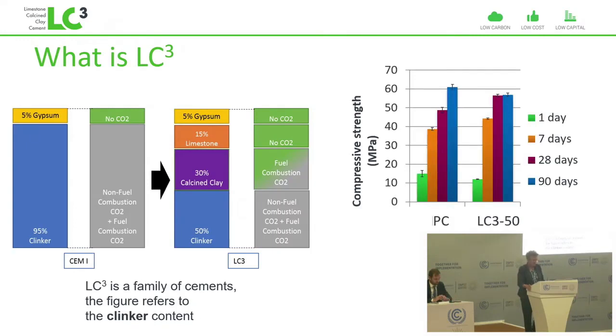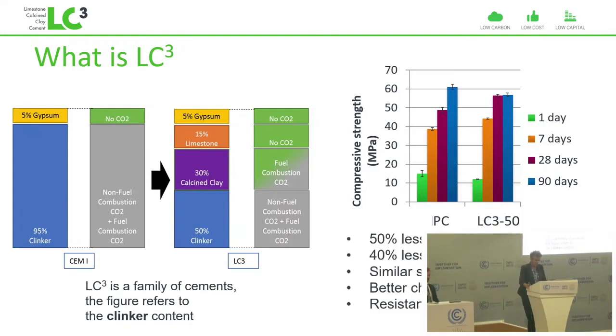So even by a few days, we have higher strength than in the reference Portland cement material. So here we have used 50% less clinker, 40% less, that equates to 40% less CO2, and we can have similar performance in some respects, notably with resistance to chlorides and alkali silica reaction, which are two problems of durability. Then we have much better performance.